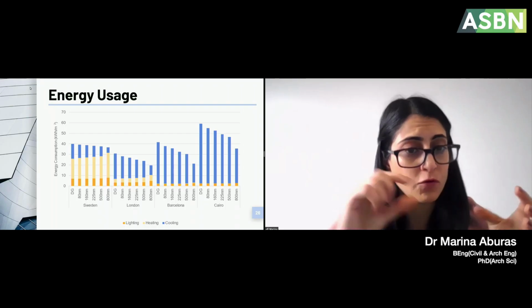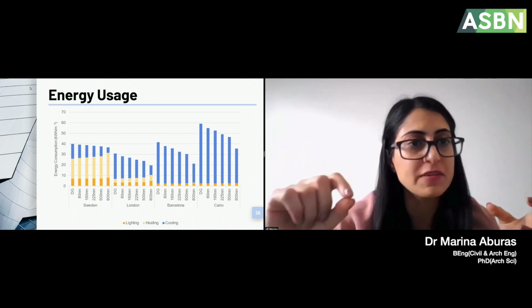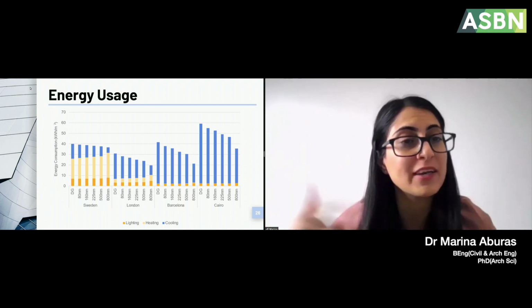So if we take just two climates so that we can delve into them, if you look at Cairo, you can see that for a double glazed coating, you've got an energy consumption sitting at around the 60 kilowatt per meter squared mark. And then all the way down to an 800 nanometer coating, you can pretty much, not quite half, but almost half that for the thicker coatings. That isn't the case in a climate like Sweden, where even though you've got the cooling energy in the blue reducing, you've actually got heating load increasing.